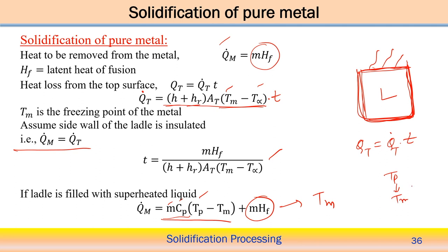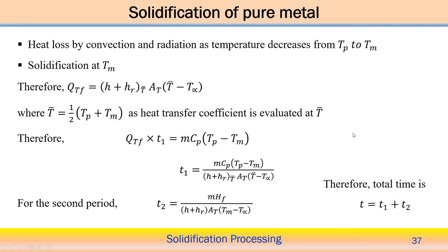So what is the heat loss? From the specific heat content, the temperature is changing. But at the same temperature the phase changes, so therefore you account for the latent heat. In that case, the total rate of heat transfer Q dot m equals m Cp (Tp minus Tm) plus m Hf.